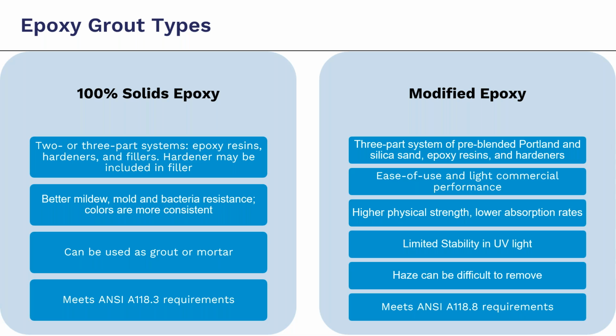With epoxy grouts, there are two different types. There are the 100% solid epoxy grouts. Those are usually a 2 or 3 part system. And they have epoxy resins, hardeners, and fillers. A hardener may include the filler, which is why you may get a 2 or 3 part system, but the filler is in there. It just may be mixed separately or together with the hardener. The 100% solid epoxies also have better mildew, mold, and bacteria resistance, and the colors are more consistent. They can be used as a grout or mortar.